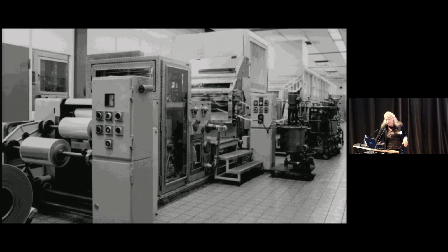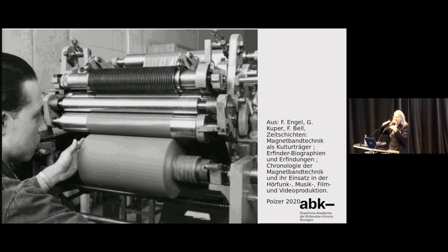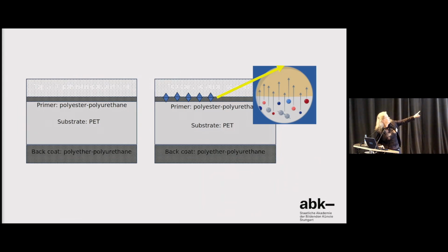Here you see the view of a tape manufacturing plant, and you see all these large, huge rollers. And these rollers, in the end, give the tape a certain pressure. It's the calendering roller, which presses together the substrate plus the magnetic coating. But the problem is that between the substrate and the magnetic coating, you have a primer, a thin layer of primer, which is polyester polyurethane. And now, if the calendering pressure is a little bit too high, then it presses together these layers, and migration starts from the primer towards the direction of the magnetic layer. This might not be harmful, this is just a production process and helps to bind.